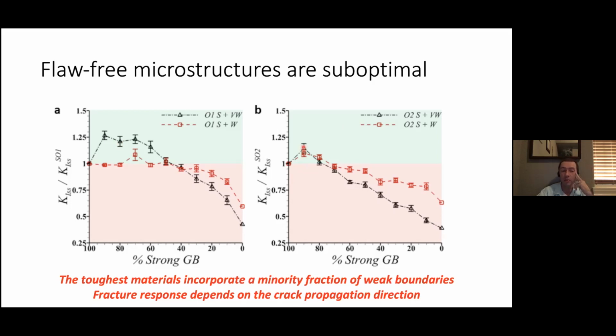So in other words, this has important implications for us because it shows us that the toughest materials actually incorporate a minority fraction of weak boundaries. Flaw-free microstructures are not optimal. And so if you're processing multi-phase metallic materials, that's good news, right? On the one hand, it means that you don't have to strive to eliminate all flaws.